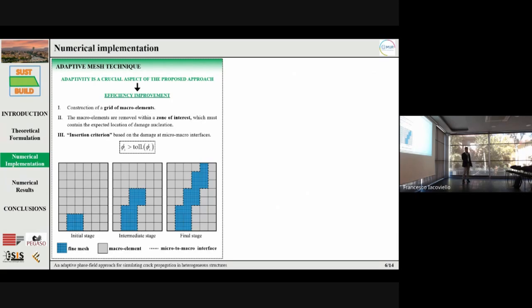The adaptive mesh technique is now presented, emphasizing its crucial role in the proposed approach for improving computational efficiency by focusing mesh refinement only in the regions where damage nucleation and propagation are expected to occur. The key elements of the adaptive mesh technique are essentially three. The first is the division of the computational domain into a grid of macro elements. The second is to remove the macro elements within a zone of interest, which must contain the expected location of the damage nucleation. And the third is to choose an appropriate criterion, which defines where and when refined mesh should be introduced. This criterion is based on the damage characteristic field variable at the micro-macro interface.